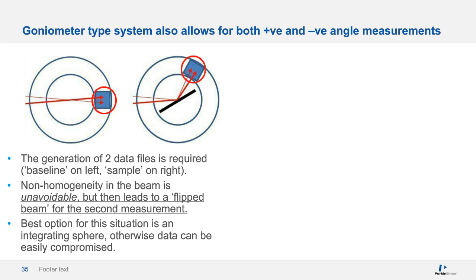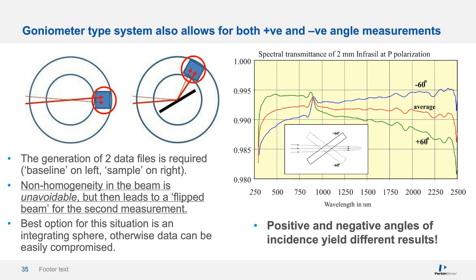Data shown on the right illustrates the beam bias as seen for transmission data for Infrasil glass at +60 and -60 degrees. The sets of data for equivalent angles are not the same, such that the two measurements must be made and an average calculated to generate a meaningful value.